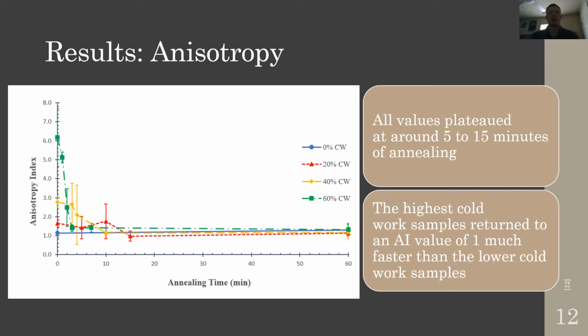And we can see from this data that all of our values returned to the original value of about 1, which would indicate circular grains. They return to that value after about 5 to 15 minutes. This makes sense, and it shows that recrystallization did happen because it creates strain-free equiaxed grains. And similar to our hardness data, we can actually see that higher cold work percentages, their anisotropy index returned to a value of 1 at much lower times than our other cold work samples. So this, again, just relates to the internal strain energy that they possess, and they require less thermal energy to return back to some of those original properties.